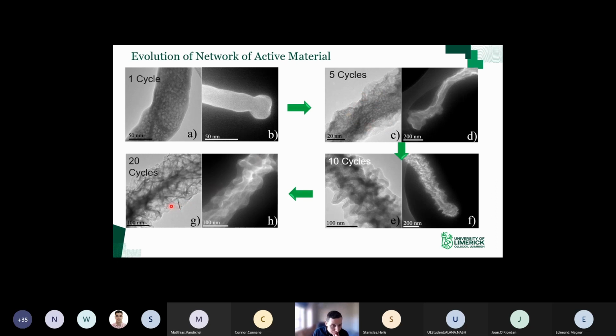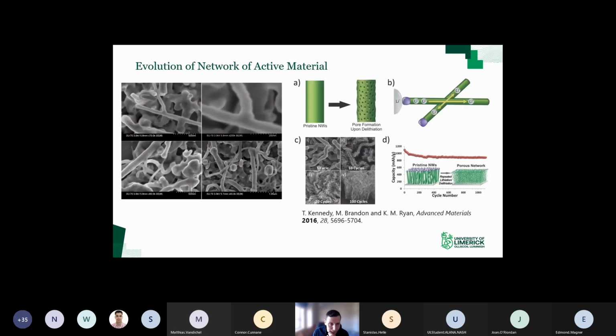Eventually, after 20 cycles, if you look at a single nanowire, you can see those ligaments beginning to form. So the nanowire is becoming more diffuse. The pores are aggregating, and now what's left behind are these ligament-type structures. So that's after 20 cycles.